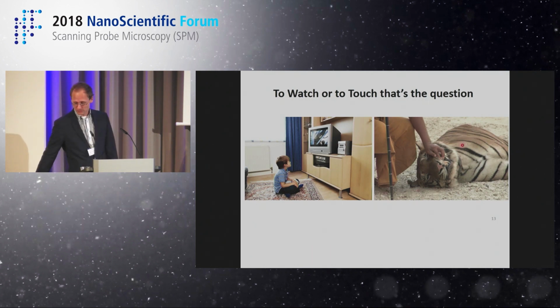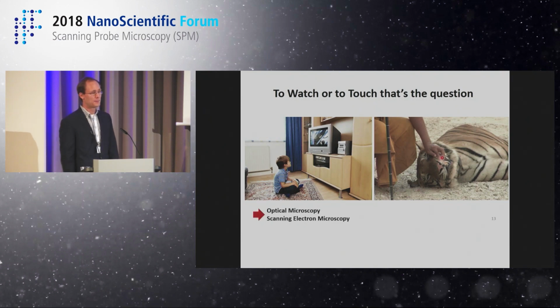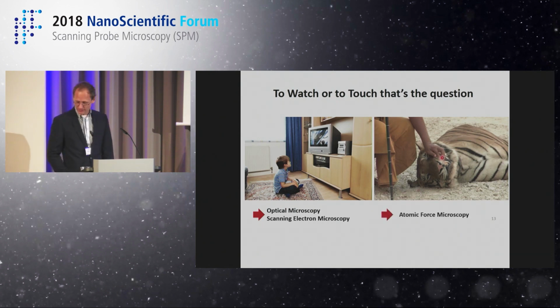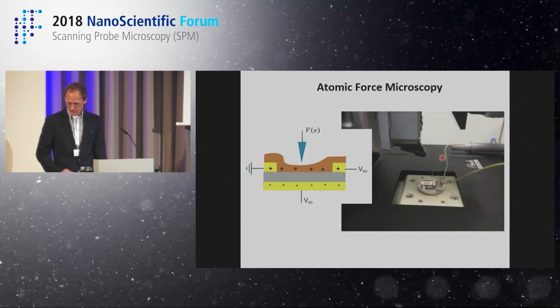Of course, people have used a lot of SEM techniques and optical microscopy in order to investigate fracture. But with photons, you cannot probe electronic properties. So the touching that is important here is to understand locally what happens to the electronics, where I have barriers in transport. And the nice thing is that that's something you can do with AFM. With AFM, clearly you have the information about the structure, but you also have the local electrostatic interaction. And let's go into detail to see this here.